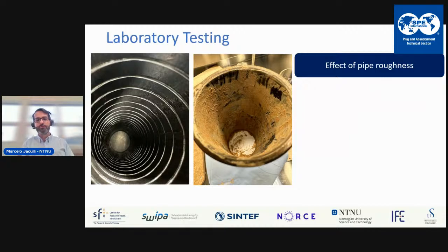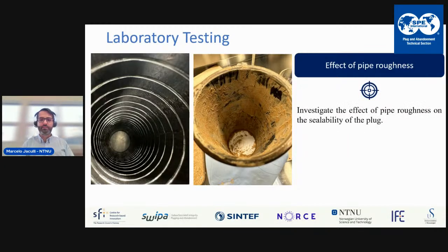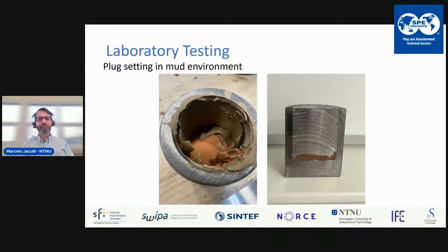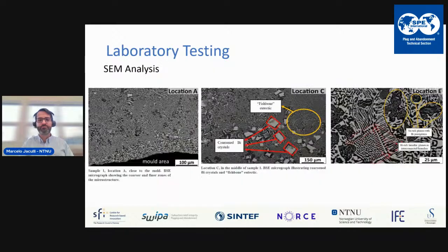But you don't want also to have some type of contaminants. So if you set this in a mud environment, you might get your mud inside the plug. This might cause some problems when the plug solidifies and contaminates, and it might not have all the properties that you want. So there is a fine balance between cleaning the pipe inner wall, but also not polishing it too much, because otherwise you lose the friction.